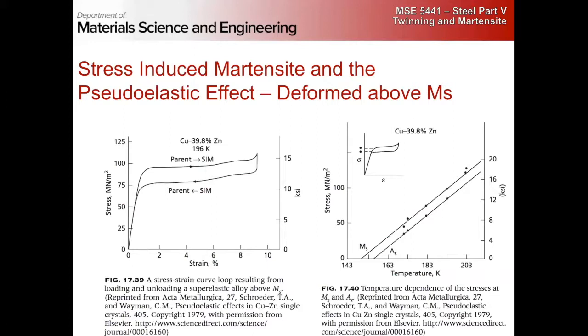But we can have stress-induced martensite as well in certain systems, right? This is essentially the shape memory alloys, right? So in SMAs, you have the pseudoelastic effect and the shape memory effect, right? The pseudoelastic effect, right? You have austenite to martensite, a stress-induced phase transformation.